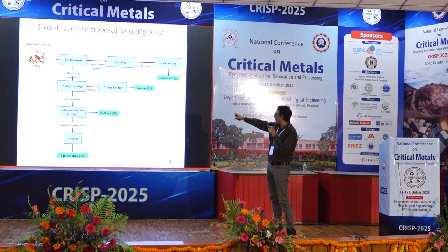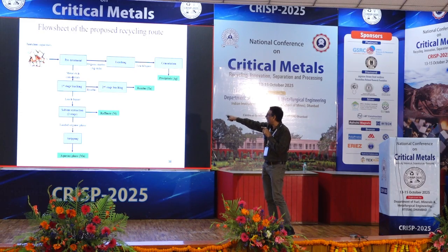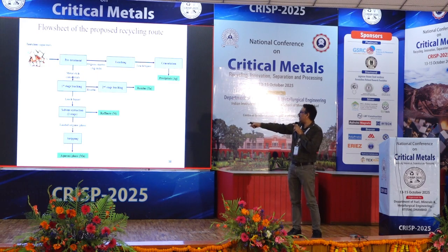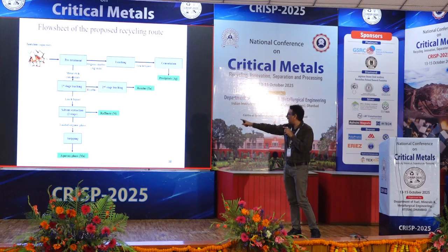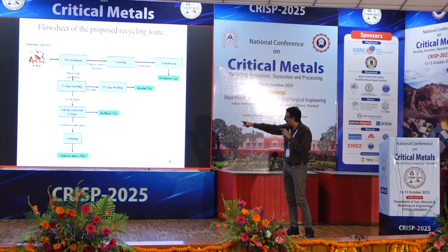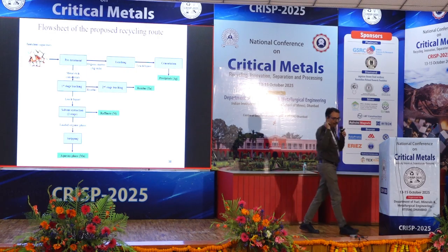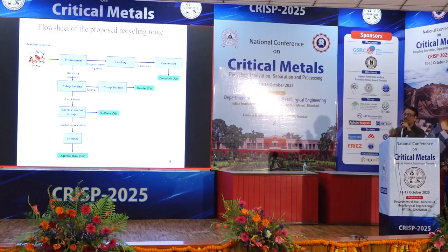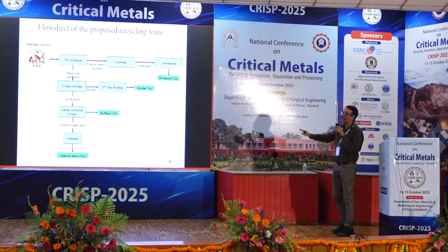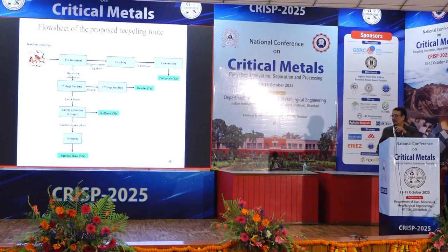And then the metal rich concentrate after the pre-treatment is treated by two-way methods, in which residue tantalum is coming, and then the pregnant solution is treated with solvent extraction. In the raffinate, manganese is first going out, then nickel is there, along with the iron, and iron is removed by simple processes: adding lime, and it precipitates out. So altogether manganese, nickel, tantalum, silver all separate very nicely.